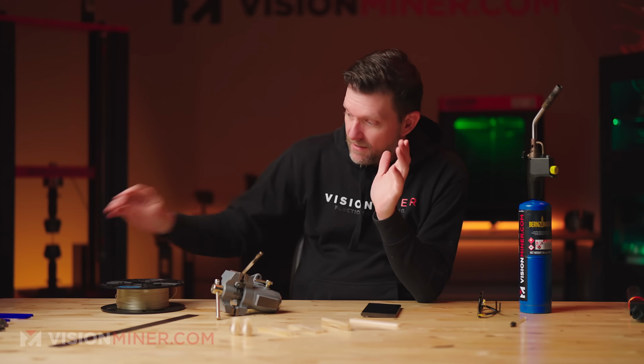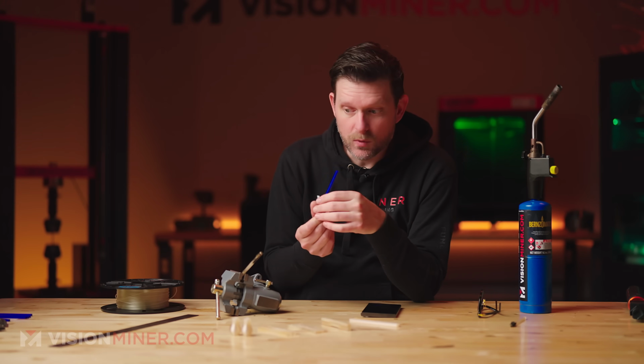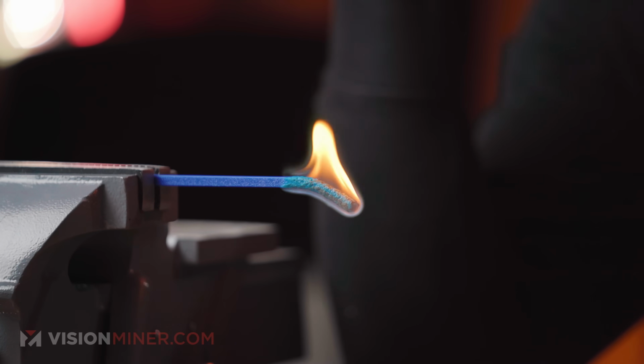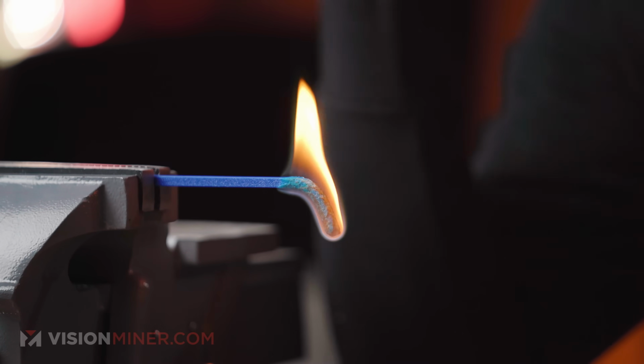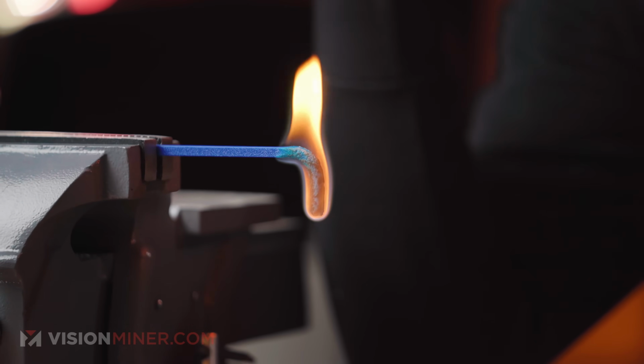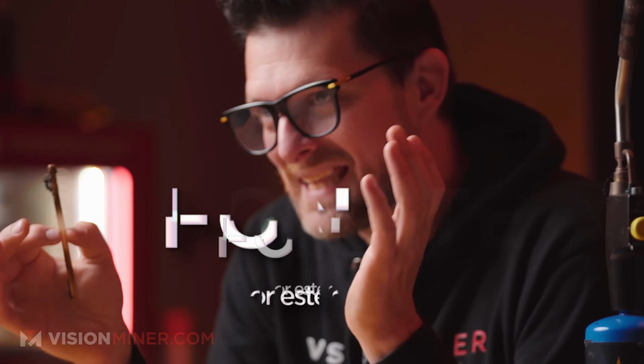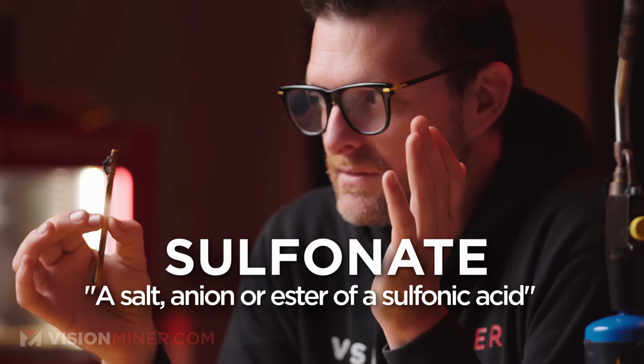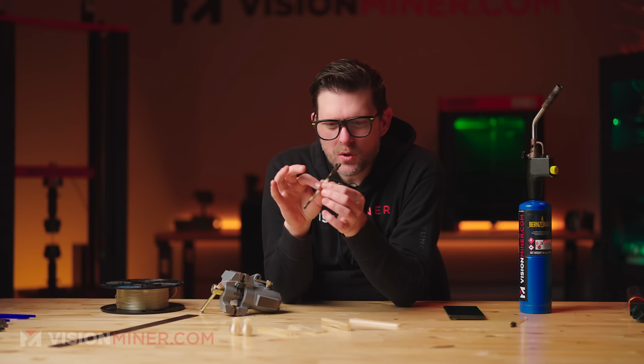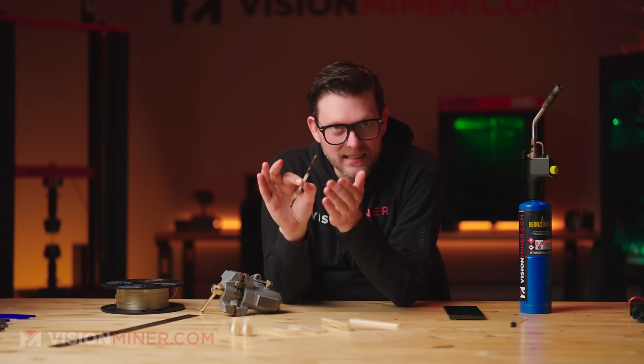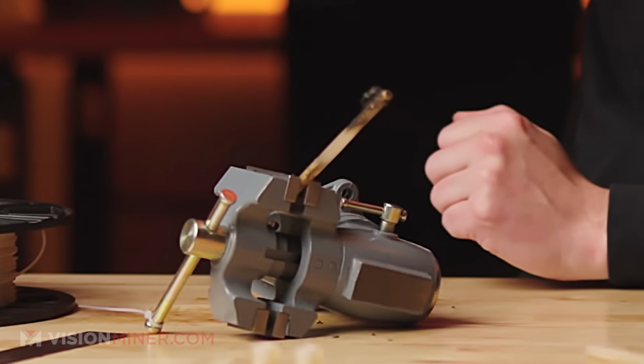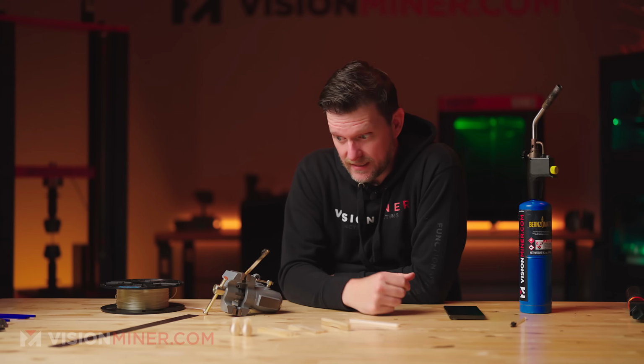Now, if I were to do this with a piece of PLA, this would actually continue to burn like a candle all the way down while letting off terribly noxious fumes. So polysulfone, sulfonates. What does that mean? Well, it means that this is far more hydrophobic than it would be without that group. It also does not melt cleanly, as you can see here. It does off-gas kind of a sooty smoke, but it's for such a short period of time that, I mean, it's actually a benefit that it's self-extinguishing.